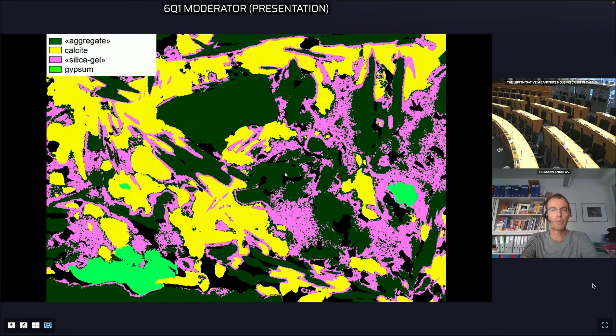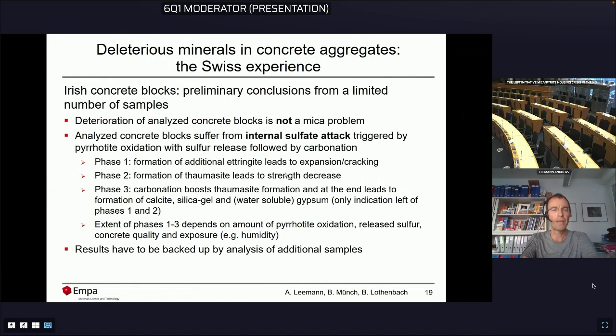So the Irish concrete blocks, preliminary conclusions from a limited number of samples. Deterioration of the analyzed concrete blocks is not a mica problem. The analyzed concrete blocks suffer from internal sulfate attack triggered by pyrrhotite oxidation with sulfur release followed by carbonation. Phase 1, formation of additional ettringite leads to expansion cracking. Phase 2, formation of thaumasite leads to strength loss. Phase 3, carbonation boosts thaumasite formation and at the end leads to formation of calcite, silica gel, and water-soluble gypsum.